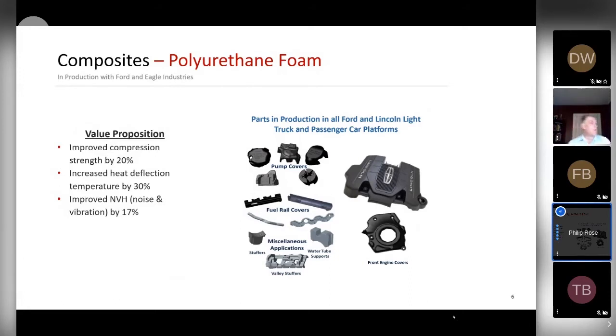Ford's use is an example where they're able to get multiple performance benefits, strength, thermal stability, and NVH from incorporation of graphene nanoplatelets. In fact, we're able to lightweight the part so that the cost to adopt our products is offset by the material savings. So it's a great example, and I believe one of the earliest of a successful commercial adoption of graphene nanoplatelets in the automotive market. Ford is now considering other materials that may benefit from use of our graphene nanoplatelets.